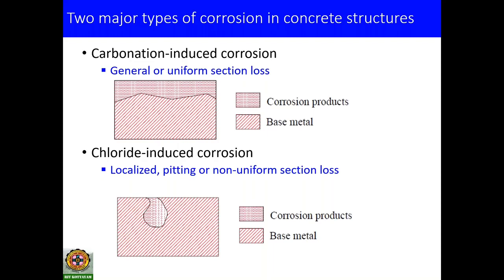So for depassivation to happen, we need certain conditions. One is, if the alkalinity is lost, that is a favorable condition for depassivation to happen. That is what is happening in the carbonation induced environment. In the carbonation reaction, the atmospheric carbon dioxide will enter into the concrete. It reacts with calcium hydroxide, which is a cement reaction product, in the presence of water, forming calcium carbonate. Because the calcium hydroxide is getting converted into calcium carbonate, the pH will get reduced, or rather the alkalinity is lost. When the alkalinity is lost, we have a favorable condition for the depassivation of the steel rebar.